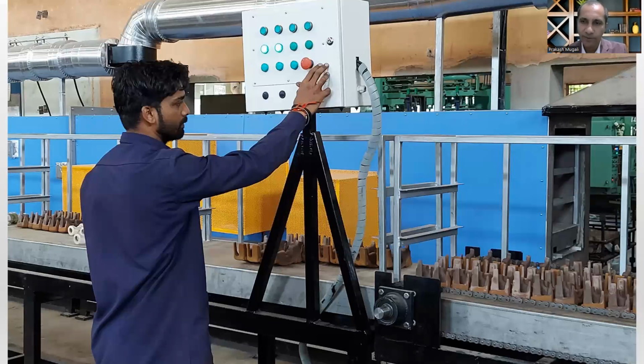A lot of water will be absorbed, so your drying time will increase, and you have to also keep higher power for drying, so your drying cost will go up. If it is a thick paint, then the moisture absorption is limited and drying will be faster. So you are recommending little thicker paint. So it is better. It gives you both power cost reduction and surface finish. So Ford cup value should be a little bit more.